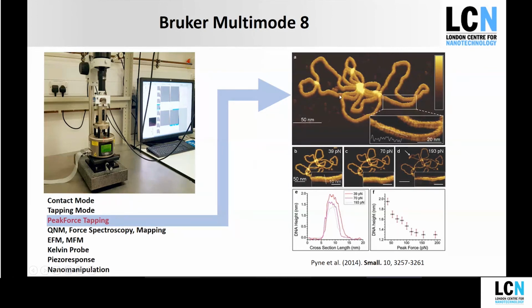And just an example, this is work done by Alice Pyne some years ago. This is done on DNA, where she managed to resolve the double helix. This is just DNA on mica in a nickel chloride buffer. You can clearly see the corrugation on the DNA helix here, and you can also see the major and minor grooves of the DNA. It's also quite important to get the force right. Here we're applying 39 piconewtons of force. DNA should sit 2 nanometers from the surface, which it clearly does there. But if you start applying too much force, you start to squash the DNA. So it's very important to get the force correct.